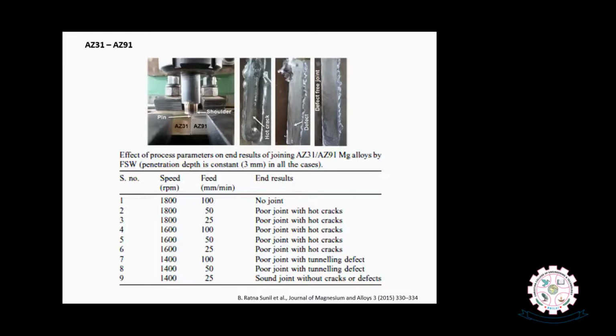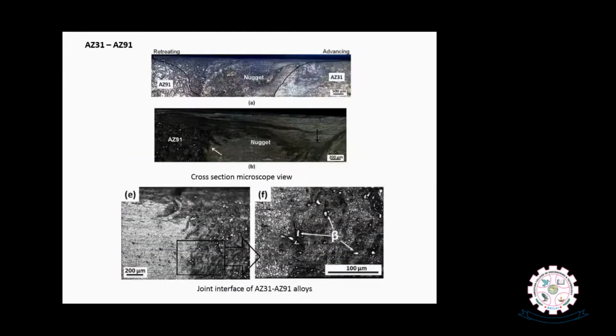At the same time, slow tool speeds and higher feed rates also will not give sufficient heat at the stir zone, and we also end up with a defect without a proper quality joint. Therefore, getting optimum process parameters is crucial in friction stir welding, particularly when you are joining dissimilar alloys, not only dissimilar magnesium alloys, any dissimilar alloys. Here we optimized the process parameters and we observed a defect-free weld joint at 1400 speed and 25 mm per minute feed. And you can see the cross section of the weld joint.